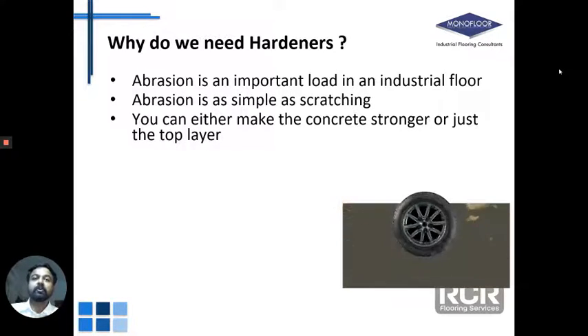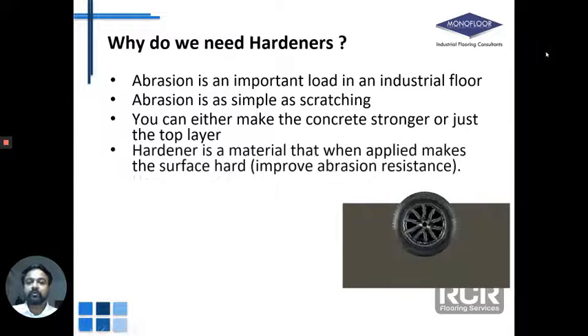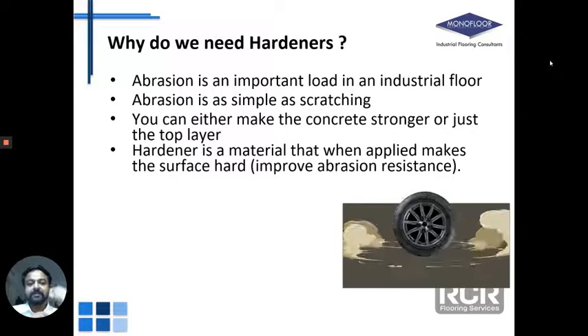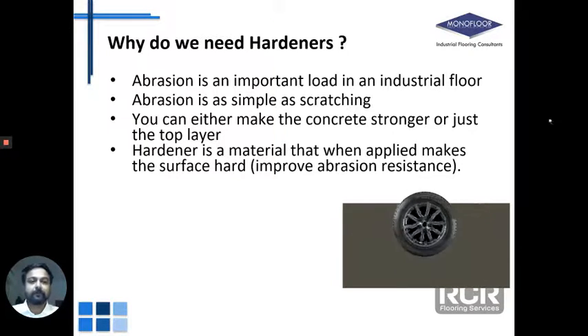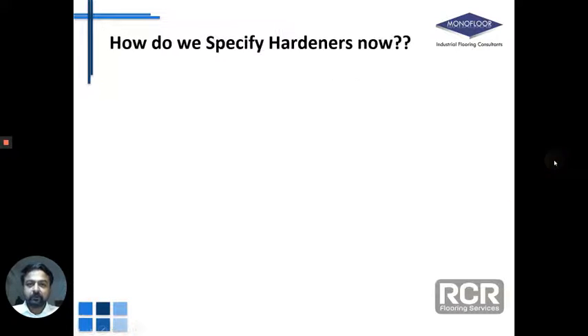But the better or more effective way to harden the abrasive layer is to improve the hardness of just the top layer. That's good enough most of the times. And a hardener, as the name suggests, is the layer that goes on top of the concrete floor that improves the abrasion resistance of the top layer. So this is the fundamental of what a hardener is about.